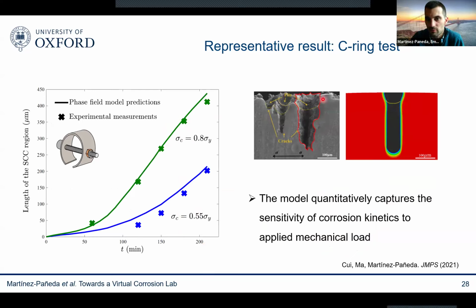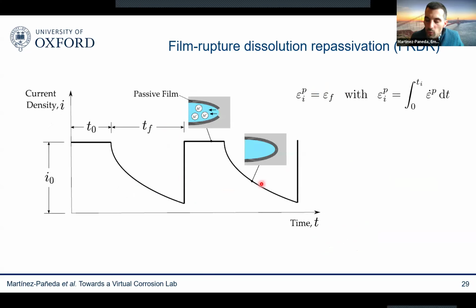We focus on only one pit, but one can model multiple pits, and you can see that the morphology of the main pit is quite similar. The other way in which corrosion interferes with mechanics is this so-called film rupture dissolution repassivation mechanism.